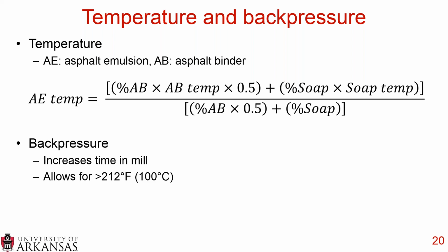Now, I've kind of danced around the topic of back pressure throughout this whole presentation. Back pressure can be used for two reasons. One, it can increase the time the material is in the mill, which will cause it to shear more, and it'll get that good particle size distribution that Chris showed on his slide. Now, you can also make asphalt emulsion at temperatures greater than 212 degrees Fahrenheit. And if you recall, 212 degrees Fahrenheit is the boiling point of water. In theory, you don't want to have those temperatures because your water will start boiling unless you put back pressure on.